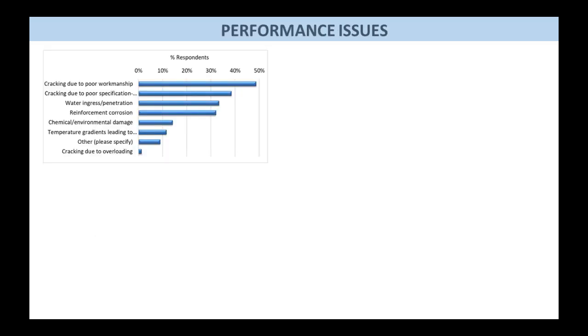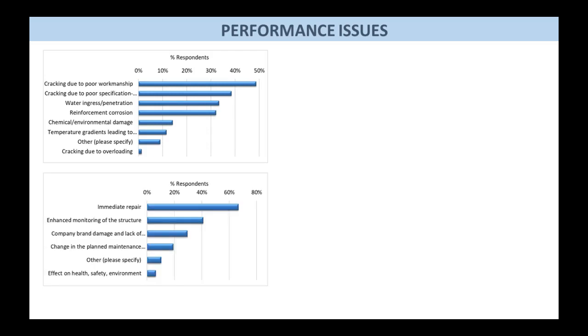So in terms of concrete performance issues, the biggest challenge, and maybe that comes from the contracting aspect, is that cracking due to poor workmanship was identified as one of the key challenges in terms of damaging concrete. Also cracking due to poor specification, followed by water ingress and penetration. And what was interesting to see is that any cracking or any defect in concrete in most cases led to immediate repair of the structure.